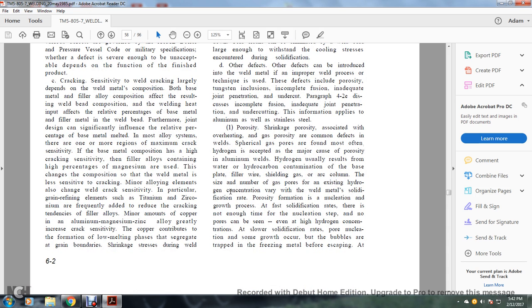Other defects can be introduced into the weld metal when an improper welding process or technique is used. The defects include porosity, tungsten inclusion, incomplete fusion, inadequate joint preparation, and undercut. Paragraph 4.2 discusses incomplete fusion, inadequate joint preparation, and undercutting; the information applies to aluminum as well as stainless steel. Porosity and shrinkage porosity are associated with overheating, and gas porosity is one of the common defects of welds. Spherical gas pores are found most often; hydrogen is accepted as the main cause of porosity in aluminum welds.